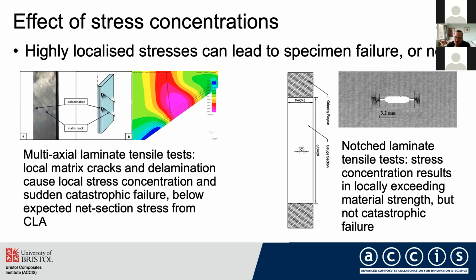On the right-hand side, we've got a different case where we've got a much higher stress concentration from a sharp notch, which leads to some local blunting due to some damage. And what you'll also see is that the crack is starting to propagate. So we have now exceeded the material strength, but in this case, we've actually got a case that local failure does not lead to a catastrophic failure, and the specimen is able to continue carrying load and will